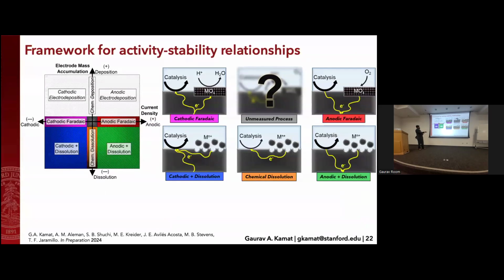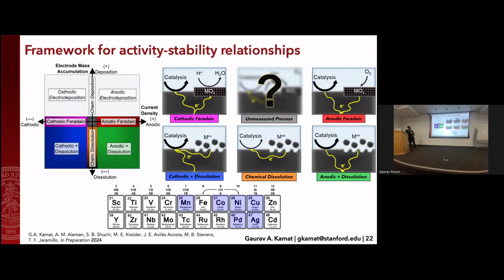So I had shown on the previous slide this cathodic plus dissolution. You have a current that's flowing net this way, but you're also supporting it with current that's due to the oxidation and dissolution of metal ions. But you can also have chemical dissolution, where there's no net current flowing through your electrode. So these are just some of the possibilities that are available. And I tested this on these specific metals, which turn out to be very interesting for oxygen reduction.